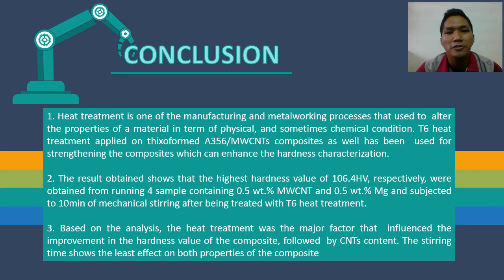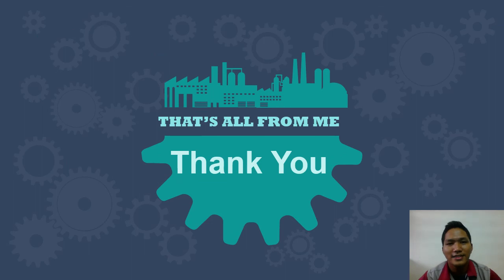Finally, we can conclude that according to the analysis carried out, the heat treatment was the major factor that influenced the improvement in the hardness value of the composite, followed by carbon nanotube contents. The stirring time showed the least effect on both properties of the composite. That's all from me.